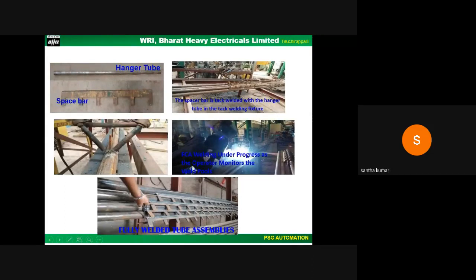A special system with a double wire welding had been tried out, and the benefit accrued by the tailor-made mechanized tube-to-plate welding system is reduced arcing time for welding, saving in cost and energy, and increased productivity by the higher travel speed obtained by the mechanized system. Without any distortion, we could achieve this, and the dependency on welder skill is eliminated.